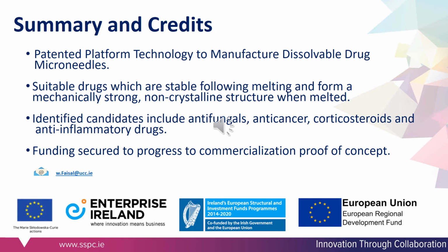In summary, we patented a platform technology to manufacture dissolvable drug microneedles. We identified the criteria for suitable drugs, which are stable and form a mechanically strong non-crystalline structure when melted. We identified potential candidates, including antifungals, anti-cancer, corticosteroids, and anti-inflammatory drugs. We successfully secured funds to progress to commercialization proof of concept of our technology. And thank you for listening.